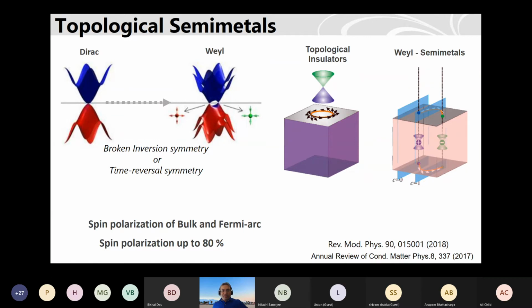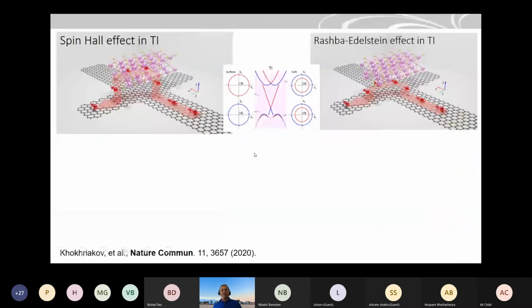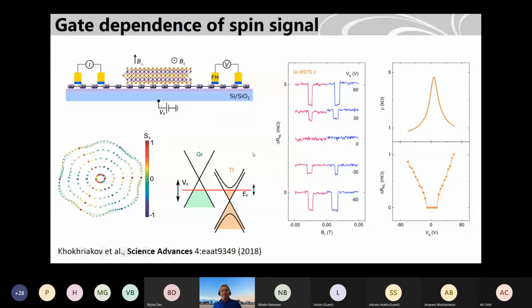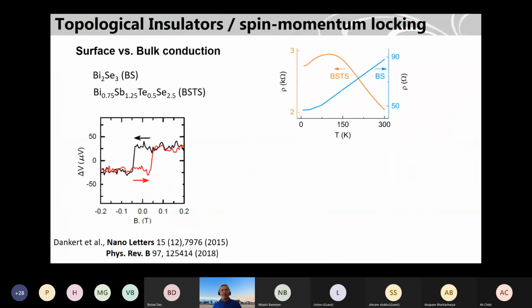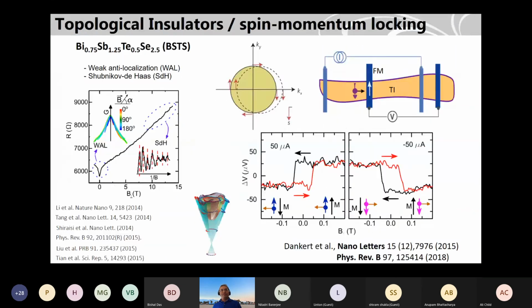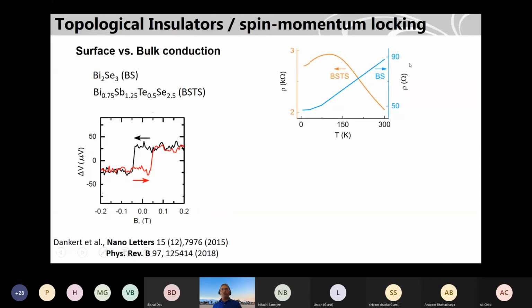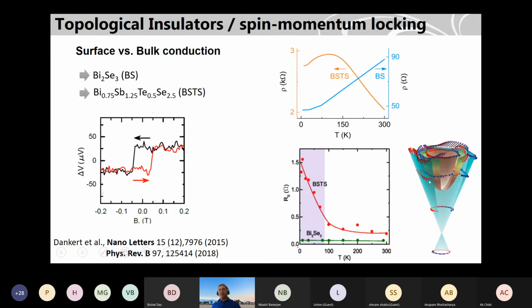Why are the RT plots of BSTS so different from bismuth selenide? What does the hump saturation mean? Okay, yeah, it's a good question. Theoretically, topological insulators, as you see, should be perfectly insulating like that. But in reality, that does not happen when you grow topological insulators. So the question is why bismuth selenide is metallic. You have some selenium vacancies when you grow them, so your Fermi level is actually not in the Dirac band gap; it's in the bulk conduction band. So that gives the metallic nature of the topological insulator. But in the case of BSTS, your Fermi level is in the Dirac band gap here, so it's below the conduction band.